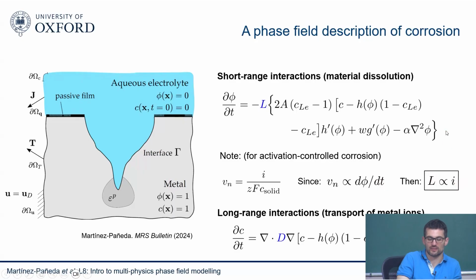And what this means in practical terms is that if you have 1D data, which we all normally do, of corrosion of a given material, you can do a 1D virtual experiment, and you can define the ratio between L and the corrosion current density. Then for any other corrosion current density in that material-environmental system, you know what your L is. So it's not ideal. L is not something fully physical. Again, it's similar to phase field fatigue. These are early days. We're getting there, but it's something that you can correlate to corrosion current density. So if you can do a single uniform corrosion experiment, then you can determine your L coefficient. There are some caveats here and there, but I think this is sufficiently close, I would say.